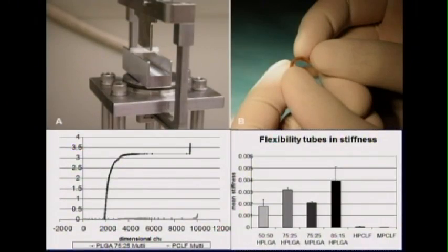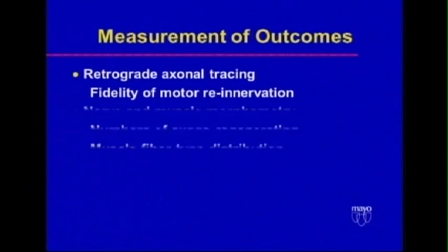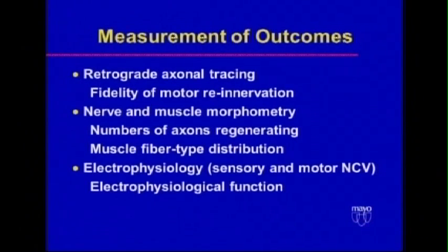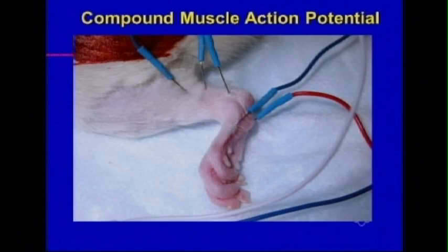So again, we changed the composition a little bit, changed molecular weights a little bit, and got the pull-out strength to be okay. And in a three-point bending, that looks like it's a little more than 90 degrees in the upper right. It may be 100 degrees. It maintains a circular cross-section past 90 degrees, which we think is okay for a first go. Outcomes, we do tracing, we do morphometry, and we do electrophysiology and gait analysis.